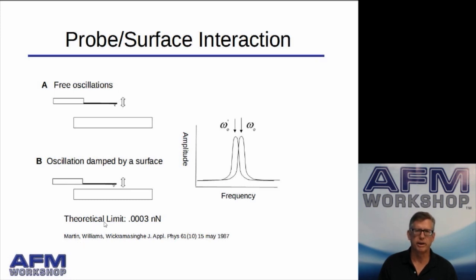And so about 20 or 30 years ago, Wickramasinghe and his colleagues, Williams and Martin, calculated the theoretical limit based on a model of this particular frequency curve and the shift in the mechanics of about 0.0003 nanonewtons. Now, I'm not sure if anybody's ever actually proven this, and I suspect that there's other calculations of what the minimum force is you can do with vibrating mode. But this is maybe an order of magnitude or two more sensitive than the non-vibrating mode or contact mode.